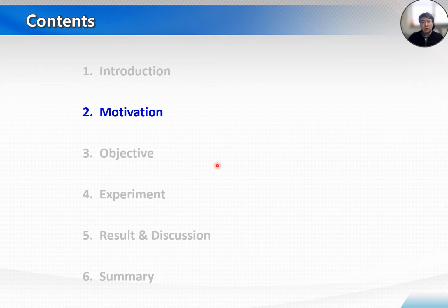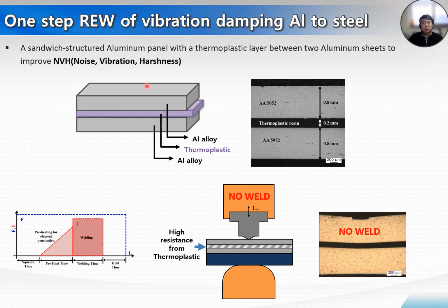With knowing all the information about the one-step resistance element welding, here is the motivation of this research. A sandwich-structured aluminum panel has a thermoplastic layer between two aluminum sheets to improve the noise, vibration, harshness properties. The assembly is made by joining an aluminum sandwich panel with a thermoplastic into a steel plate. At this time, our laboratory proposed a two-step resistance element welding process. However, in the case of two-step resistance element welding, quality problems such as delamination of the sandwich panel occur during the pre-assembly process of punching the element into the upper aluminum plate. So we attempted to solve this problem by applying one-step resistance element welding.